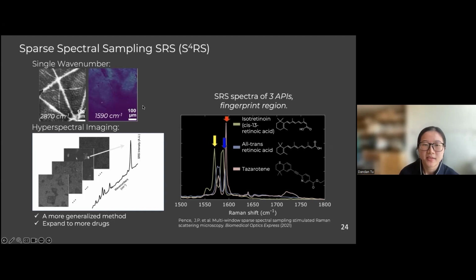So moving forward, our lab focuses on using the sparse spectral sampling SRS, S4RS, method, which looks at multiple spectral peaks or even spectral segments to image the drug instead of using only a single wave number. In this way, we are not limited to drugs that have a very strong signal at one wave number. So we can really expand to image more drugs, and then we can study more topical drugs on skin in the field. Here is an example showing that we can use SRS spectra to distinguish three APIs that have very similar structures, but we can differentiate them by different peaks.